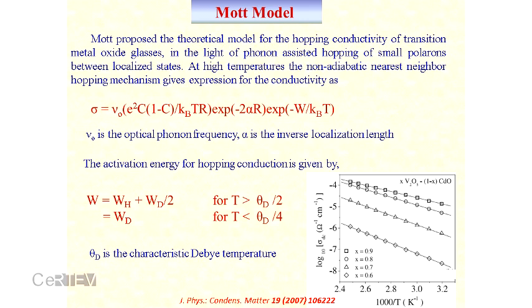And we have one important term, alpha R, the exponential term, which is the localization term I have described, the localized wave function in a disordered material. And this is the activation energy. So these are the several terms, and this activation energy depends on temperature. I have shown it in the picture.